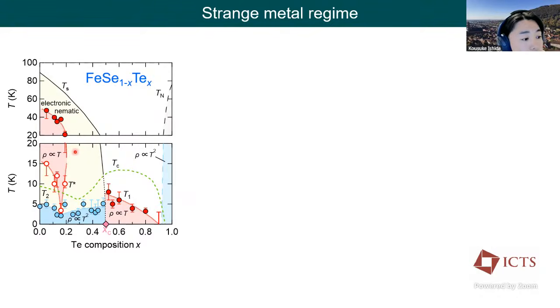The first one is inside the nematic phase, but here we can clearly rule out that the nematic fluctuation drives this strange metal, because it should rather be suppressed inside the nematic phase. Spin fluctuation might be a candidate for the driving source here, but it is unclear why T-linear resistivity is more stable at x = 0.16. The origin of strange metallicity here remains an open question.